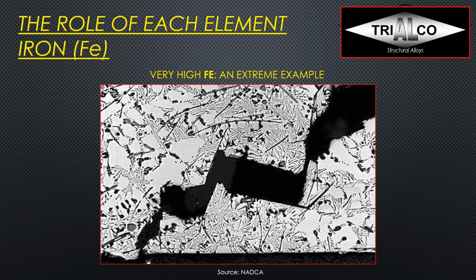Here we can see a very nice example, or an extreme example I should say, of iron in a die casting alloy. You probably recognize this. It looks similar to what we've seen before. It's an A380 with a very high iron level, and I have seen 380 die casting sometimes with up to 3% iron, because very few die casters actually use a spectrometer to check it. This was just cast, and we can see the crack is along these iron needles, which are actually platelets in 3D.